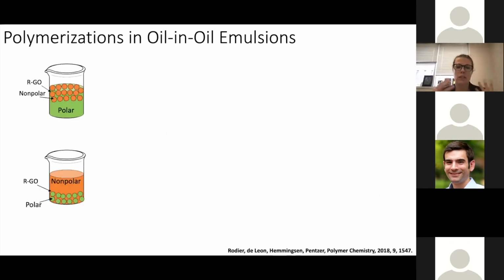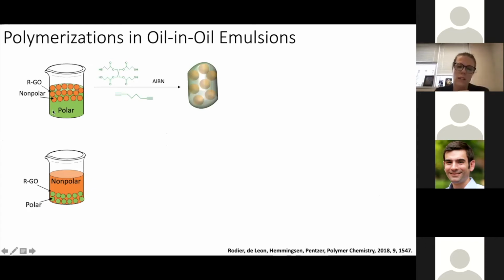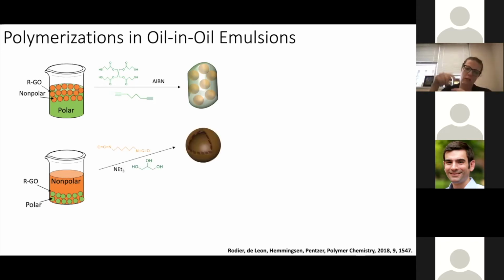And so Brad took the system and looked at doing polymerizations in these oil emulsions, or non-aqueous emulsions, with the idea being reagent compartmentalization. And so if the continuous phase, the green here, is a monomer, in this case a tetrathiol and a dialkyne, and there's AIBN present, you could then do thermally induced thiol-yne polyaddition polymerization and access a solid structure in which there are pockets where the droplets used to be, so a closed cell foam. Alternatively, provided we get mass transfer across the interface, if one reagent is in the continuous phase and one reagent is in the discontinuous phase, interfacial polymerization would occur only at the interface where those two reagents find each other. And we would then access a polymeric shell around the nanosheets.